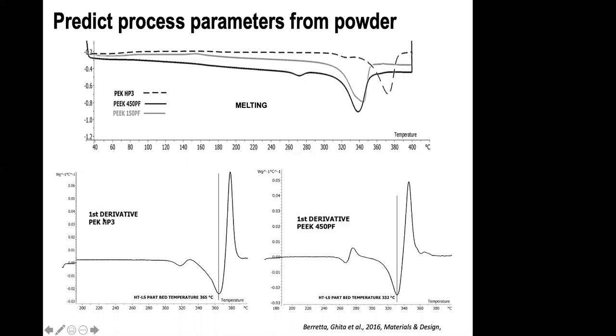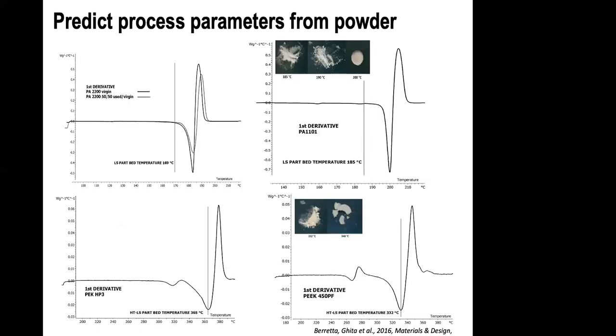for example, PEK, you can see on the picture, PEK HP3, and for example for PEEK, 450 PF of Victrex grade, that the temperature at which we operate the system is well within the melting peak, and actually it's spot on the minimum point of the first derivative. So we tried to check whether this method works for nylons, and discovered that it doesn't follow the same trend.